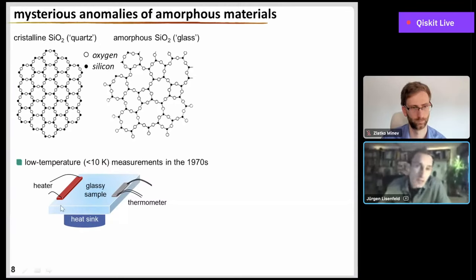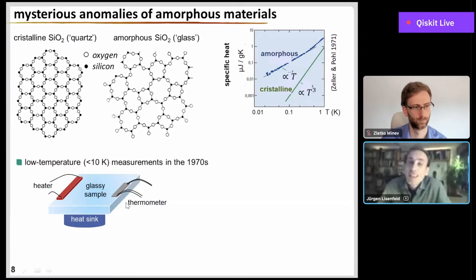And then putting just a heater on one side and a thermometer on the other side, you can already measure something like the specific heat, for example. And now it turns out that if you measure the specific heat of an amorphous material, then it will be much higher than that of a crystalline material, even containing the same atoms. And the specific heat tells you how much energy you need to apply on your heater to heat up this material by a certain degree of Kelvin.